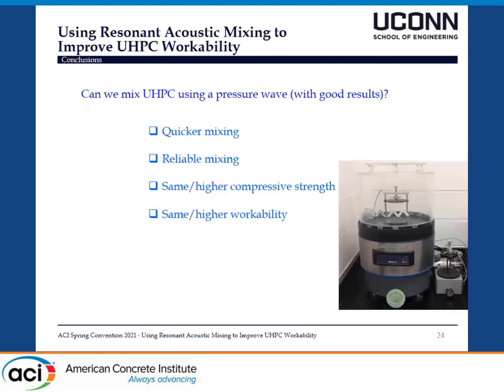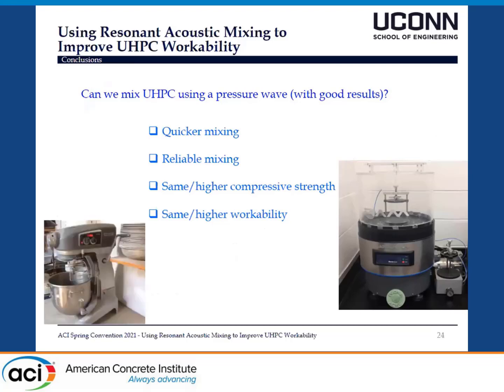So coming back to the question, can we mix UHPC using a pressure wave with good results? Good results meaning quicker mixing, reliable mixing, same or higher compressive strength, same or higher workability, compared to a Hobart mixer or your standard mechanical mixer in a lab. Then yes, it can mix quicker. It can be more reliable in terms of getting the same results one after another. You can find same or higher compressive strength, and we were able to find same or higher workability.